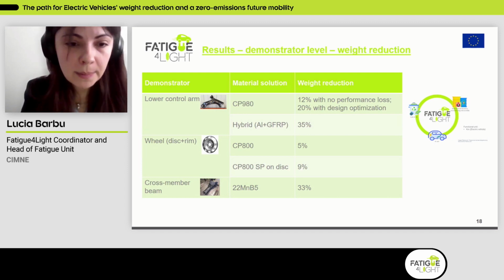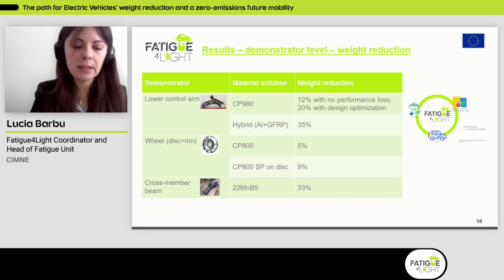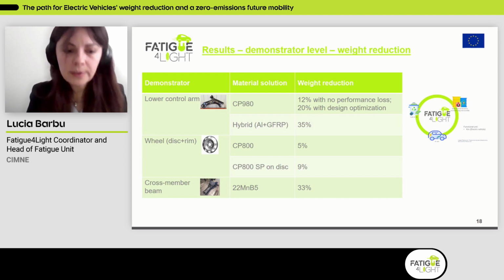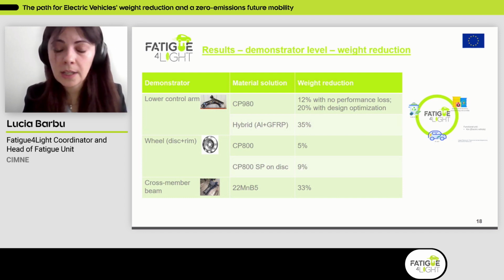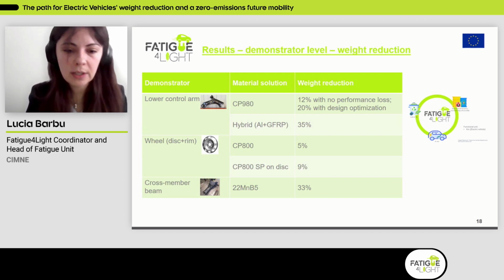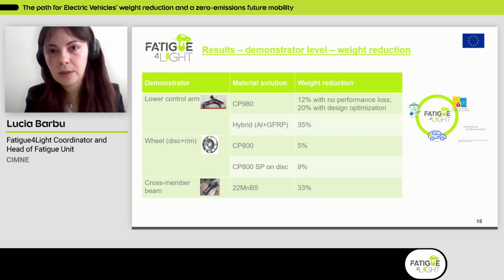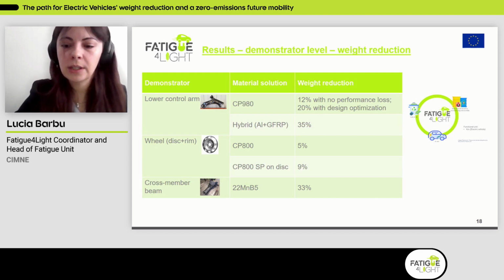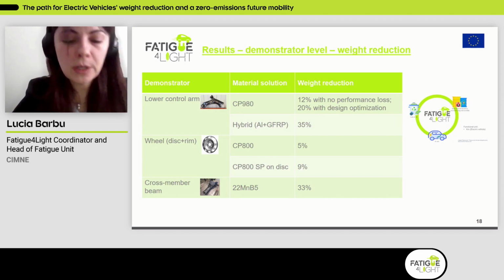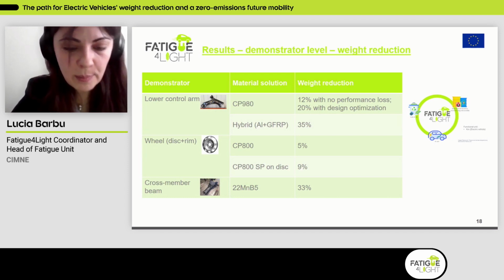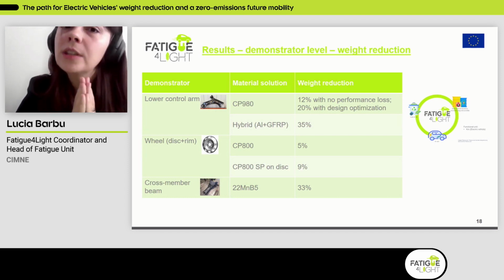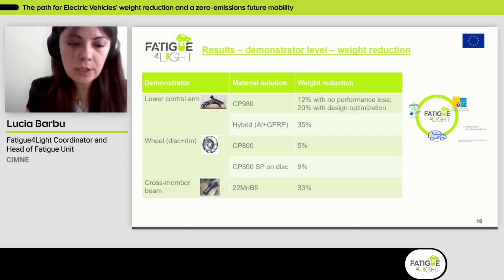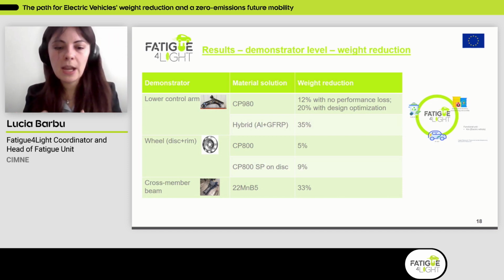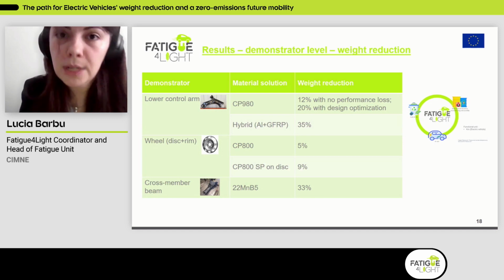And for the cross-member beam, when we used the press-hardened steel, we observed a reduction in the weight of about 33%, which actually shows you the really great potential of this material to be used on heavy-duty vehicles. But I don't want to leave you only with this perspective of weight reduction. This is not the only important thing when you consider the performance of the different materials today with respect to CO2 emission, with respect to end-of-life considerations, so recyclability, etc.